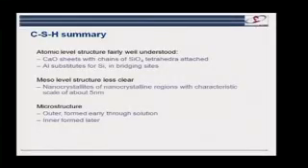So just to summarize that part on CSH, coming back to it on the atomistic level, we understand fairly well what's going on, although it is a bit complex because we can have these chains being incomplete. We can have aluminium substituting for silicon. The meso level is less clear because really it comes down to the fact, are these nanocrystallites joined together or not?